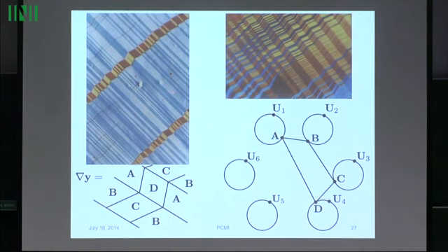It's not flat now because it was transformed from a high temperature phase. It was polished in the high temperature phase. Okay, and then it was transformed, and we got this ripply surface with all these roofs on it. Now you polish it off in the low temperature phase, and you transform back to the high temperature phase. Now the appearance of the specimen will be full of roofs and atomically sharp interfaces. The surface will be all rippled up in the high temperature phase.